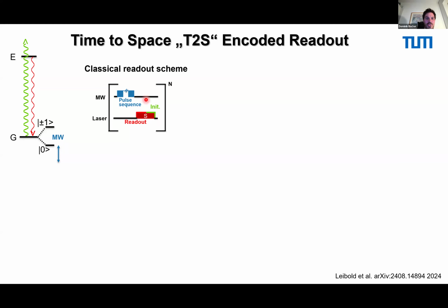So if you have the NV center I showed you before, you see it here, we have the optical excitation, you have the microwave pulses here. And typically we have our pulse sequence, we have the readout, we initialize the spin system and start again. This is all done basically, see down here. So what we do is, we manipulate the spin with microwaves, and then we basically read out and re-initialize the quantum state, okay? And of course, if you would do imaging now, you would go to the next spot and repeat everything again, apply the microwave pulse sequence, do the readout and then initialization.